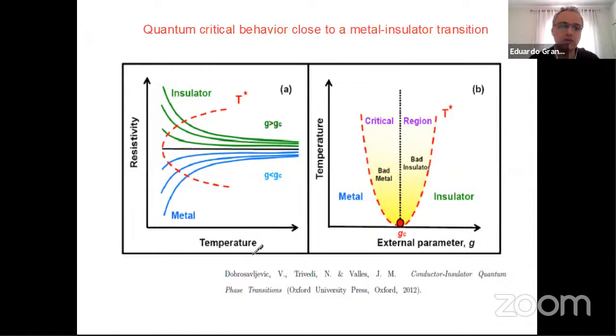And in principle, you should be able to induce a metal-insulator transition. If you have a critical parameter like pressure or doping or some other tuning parameter, and you start with a tuning parameter above a critical value, you may have an insulator phase. And if this tuning parameter is reduced, it may lead to a metallic phase. And at this transition, at this point where you have critical behavior, new physics may arise. So you may look at a temperature versus external parameter diagram. On the right side, you have the insulator behavior. On the left side, you have metallic behavior.